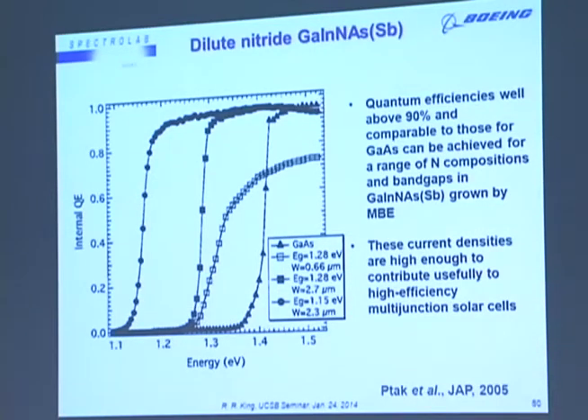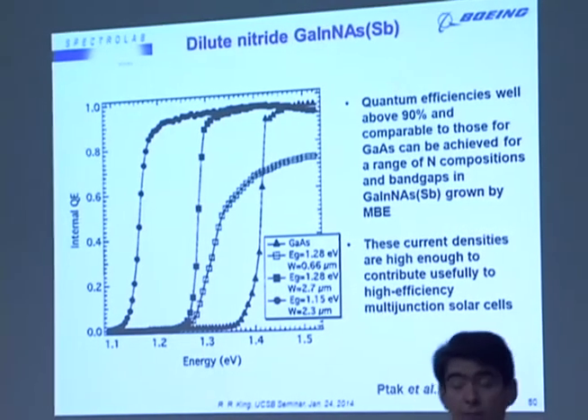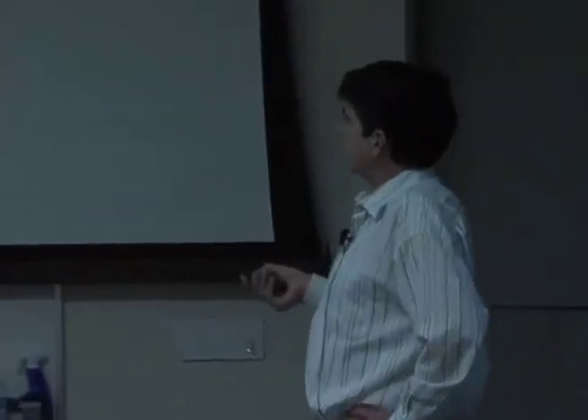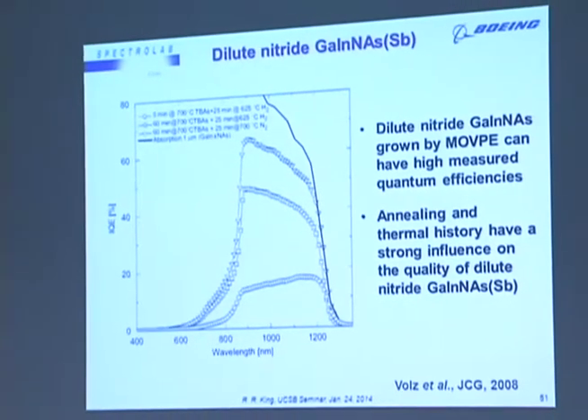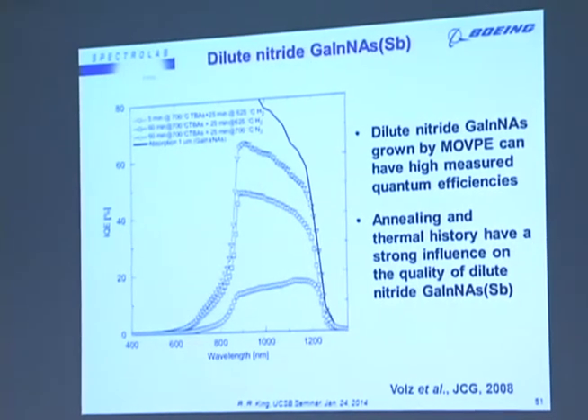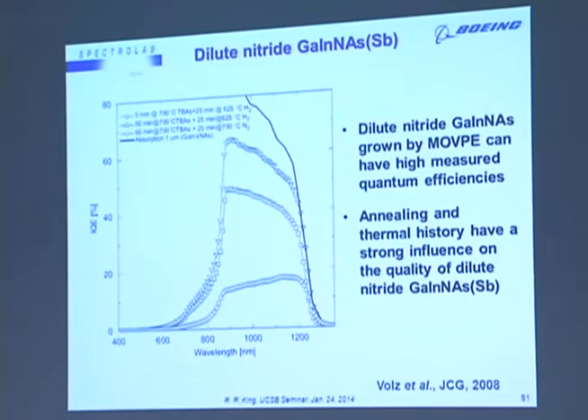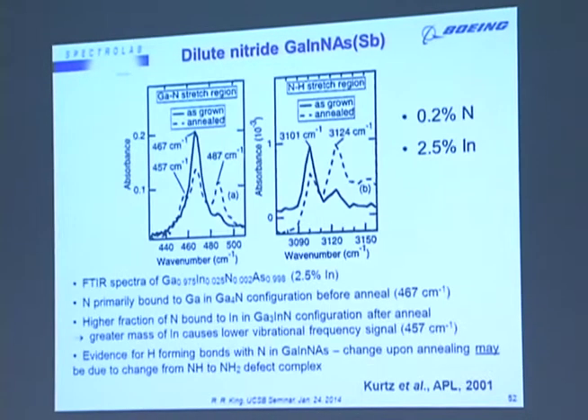So in these gallium nitride arsenide films, we can achieve really quite good internal quantum efficiencies. So internal quantum efficiencies well above 90%, making this definitely a very viable solar cell subcell material to use in a multi-junction cell. Those were dilute nitride cells grown by MBE, but the dilute nitride materials can also exhibit good internal quantum efficiencies when grown by metal organic vapor phase epitaxy as well, or MOCVD. But the annealing and the thermal history have a strong influence on the quality of the gallium nitride arsenide.